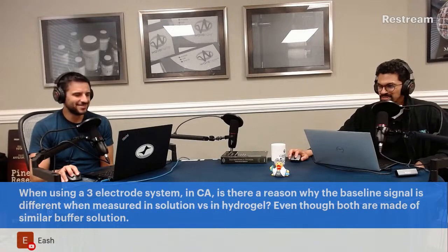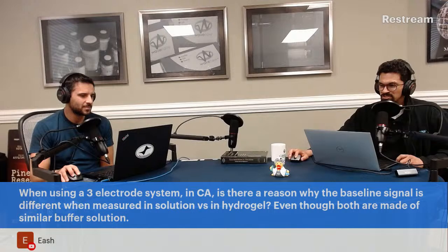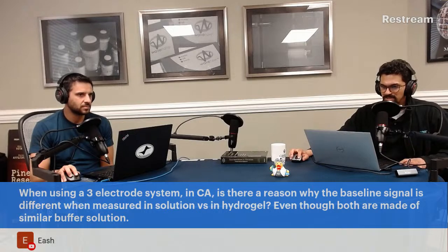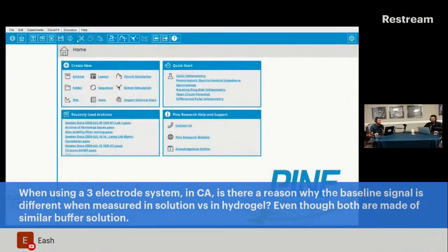Is there a reason why the baseline signal is different when measured in solution versus in hydrogel, even though both are made of similar buffer solutions? So that is interesting. The only thing I think, if literally that's the only difference, is that the diffusion coefficient will be different. Would it just be the double layer strength? Because the diffusion coefficient difference, based on the Cottrell equation, would affect how long it takes to get to the baseline. Yes. But the baseline itself being bigger is the equivalent of scanning faster, you get more double layer. So would it have to do with a thicker double layer or not?